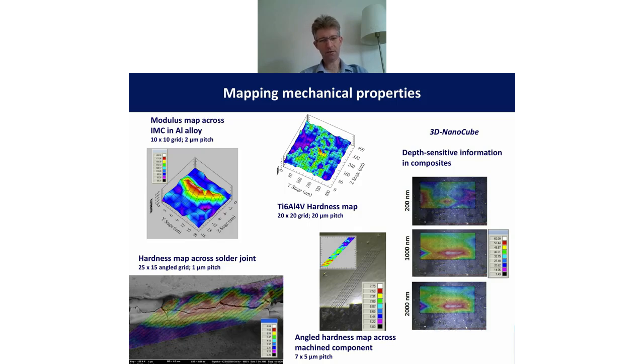Solder joints are particularly important because solder joints can be brittle, and this can lead to reliability problems. So this is a mechanical property map of lots of finely spaced indentations, and you can see that the region in the vicinity of this joint is much higher hardness. The red is the higher hardness, and actually you can see that it has led to reliability problems because it's actually cracked after testing. And you can look at machine components,